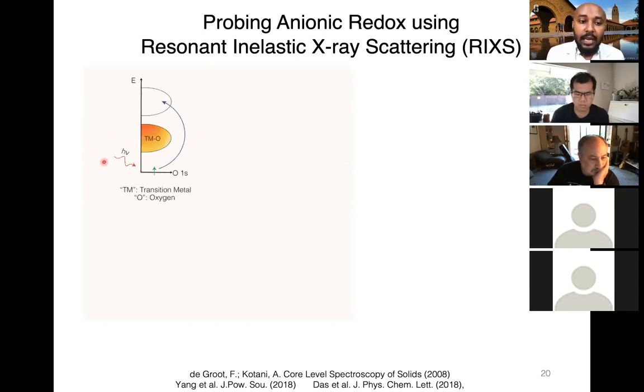There's a two-step process when you perform this measurement. The first step is we come in with certain photon energy to be able to excite an electron from the core orbital, in this case, oxygen 1s, because we would like to understand the oxygen. And this excitation process will move the electron from the core to unoccupied orbitals.